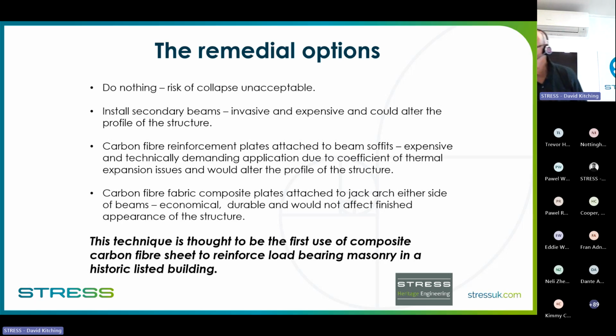So that's not the answer, but there is an answer using carbon fibre, and that's to use a fabric. And instead of strengthening the cast iron beam, you actually make the brickwork span laterally rather than circumferentially. So it will spread the balcony loads down onto the beams, but if you make it act as a beam as well, spanning from the wall out to the columns, then in fact it will take load off the beam, and that's the secret of it.